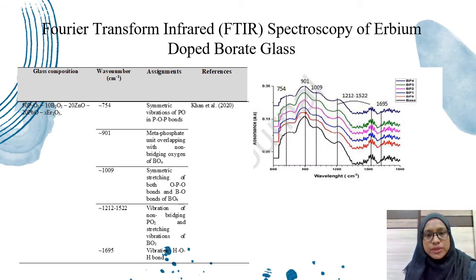FTIR spectroscopy of erbium doped borate glass by Khan et al. 2020. At 754, the symmetric vibration of PO in POP bonds. At 901, the metaphosphate unit overlapping with non-bridging oxygen of BO4. At 1009, the symmetric stretching of both OPO bonds and BO bonds of BO4. At 1212 until 1522, the vibration of a non-bridging PO2 and stretching vibration of BO3. And lastly, at 1695, the vibration of the HOH bond.